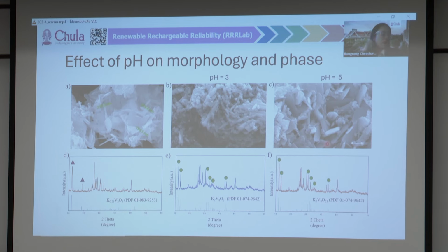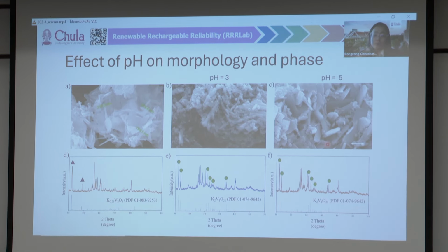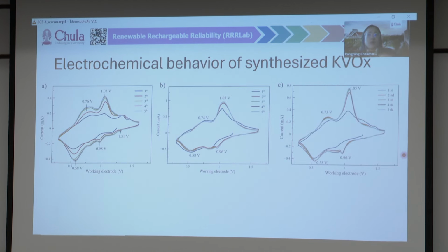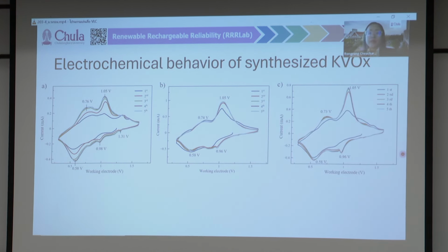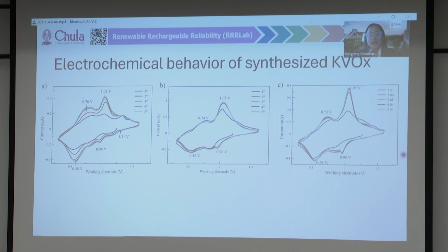While if you compare with the control, the phase that we got for the control is different. So the first message here is that the pH during synthesis is kind of important to control whatever phase you would get out from your cathode materials. And then we go further to explore the electrochemical behavior of this cathode material.